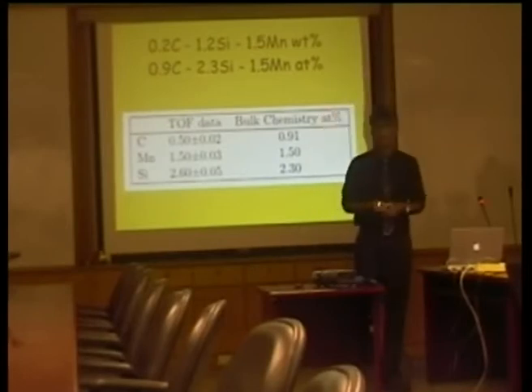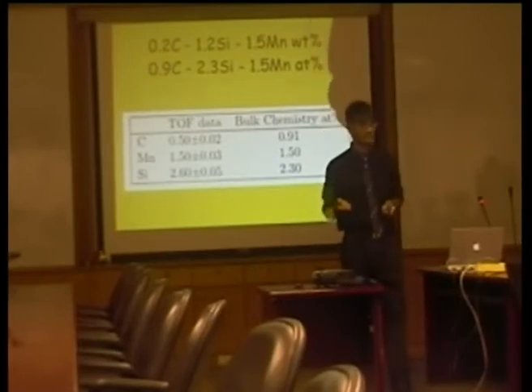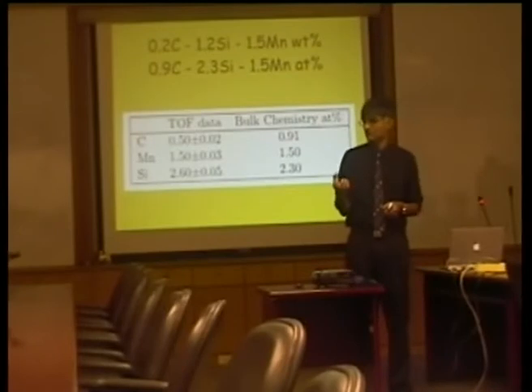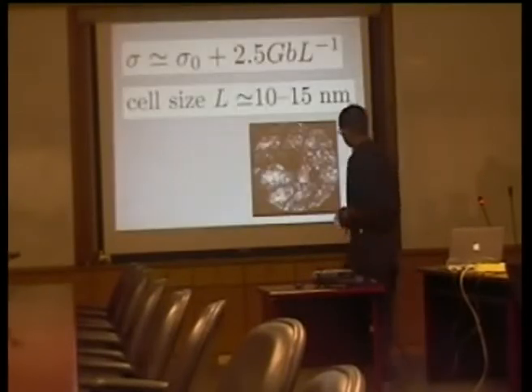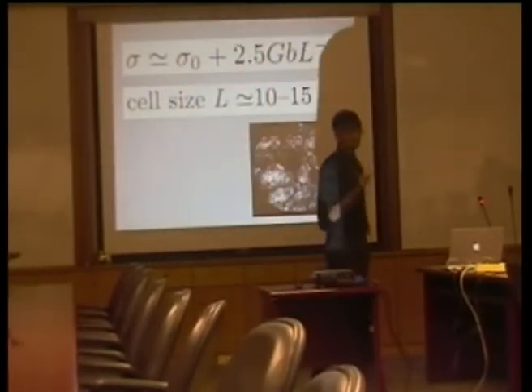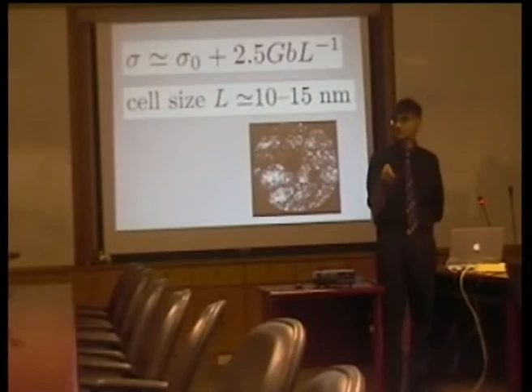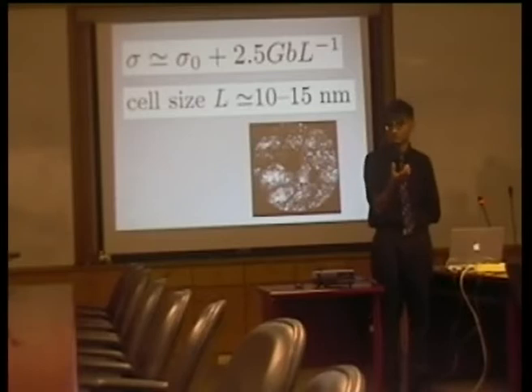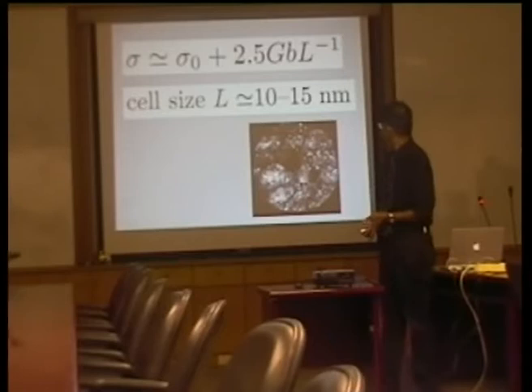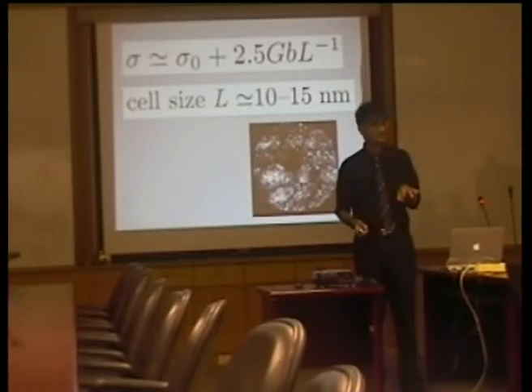So let's now think about where the strength of this material comes from. We've got 5.5 gigapascals measured strength. Well, the most effective strengthening mechanism is grain size. If you can make the grain size fine, then you can achieve huge strength, as long as the grain size is very, very fine, because strengthening due to grain size varies with 1 upon the grain size.